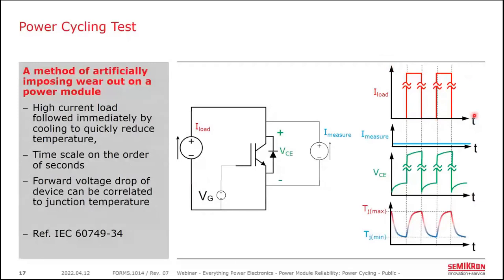The magnitude of this current is selected so that the conduction losses in the device give you a certain temperature rise, a delta T that we discussed earlier. The module is mounted on a cooling plate of some type to reduce the junction temperature back to its starting point when the load current is not flowing. So we're actively cooling this device. So we have a method of accurately heating and cooling the device at a fixed interval, but we also need a method of accurately measuring the temperature.